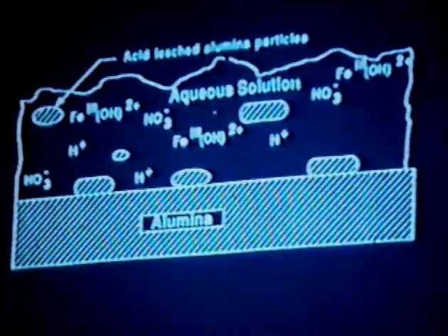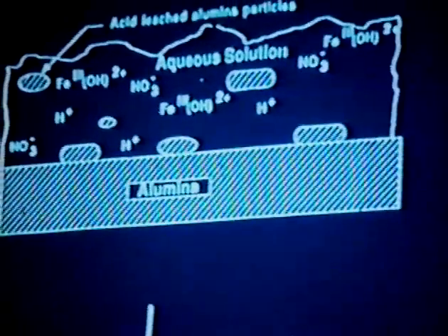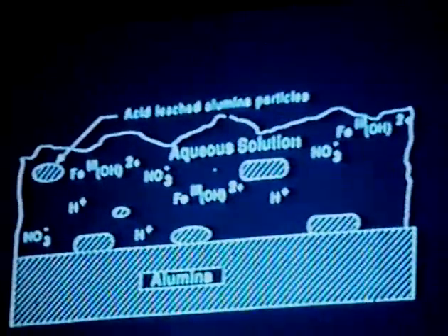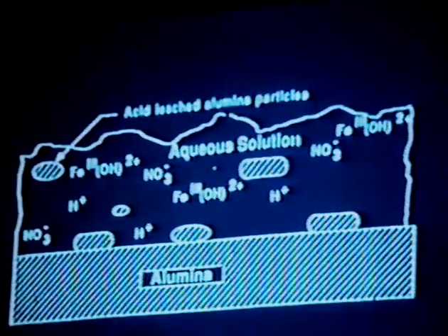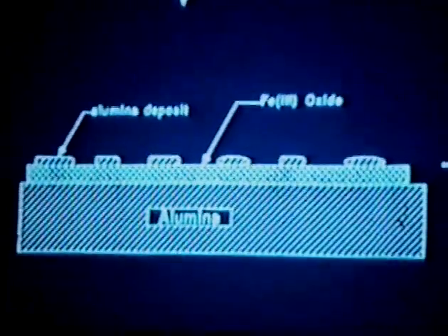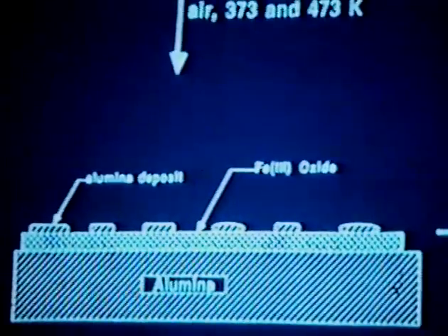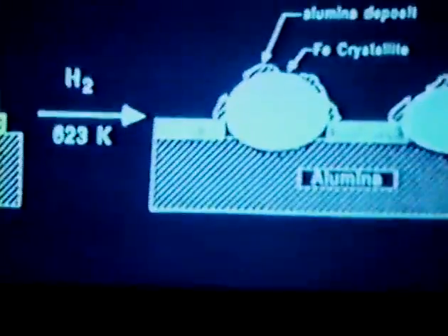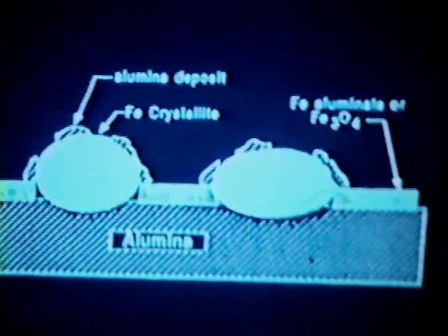So our studies indicated that even on alumina supported catalyst with conventional preparation, that is, for example, here catalyst prepared by impregnating a nitrate salt of iron, we find that upon drying this aqueous impregnated material, hot acidic solutions form in the nearest proximity of the alumina surface, which etches some of the alumina and dopes the metal oxide layer. And upon reduction, we end up having crystallites that are decorated with these doped aluminum oxides. And one could envision that the extent of this decoration could vary with varying crystallite size.